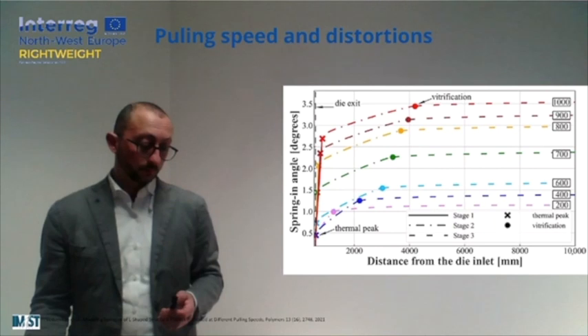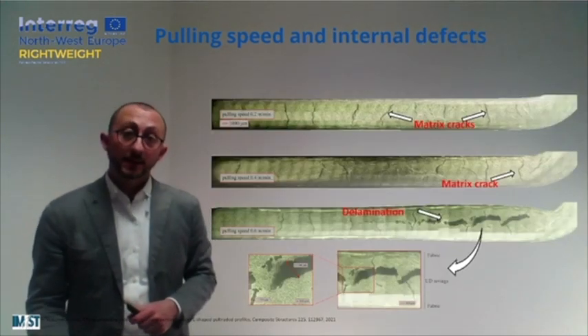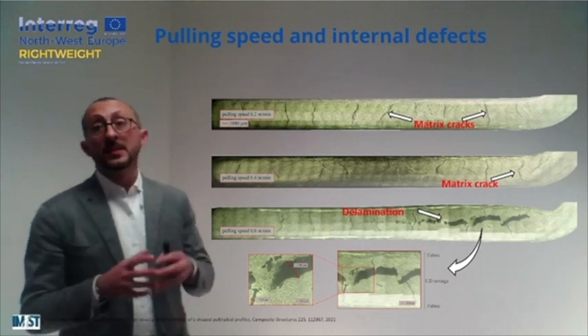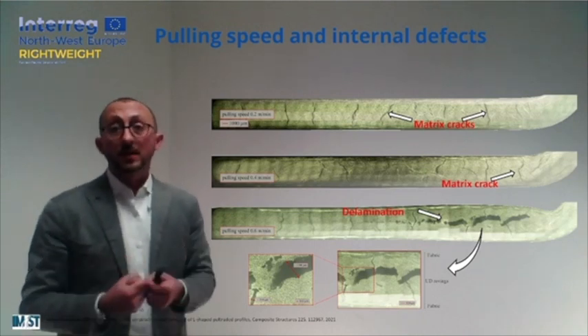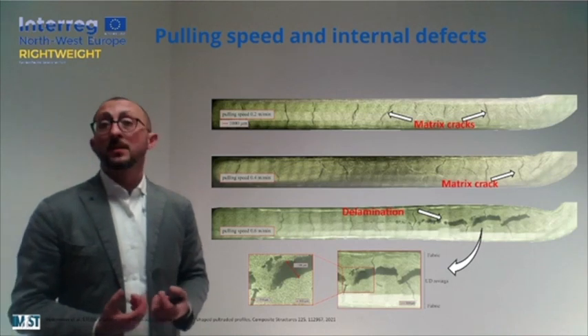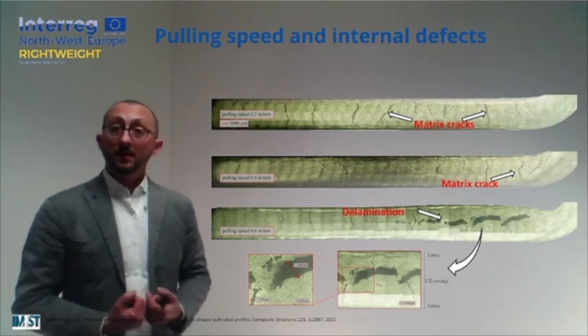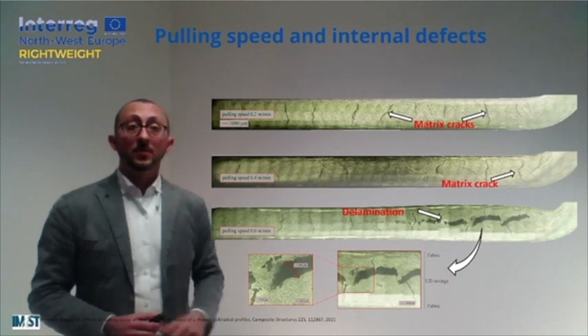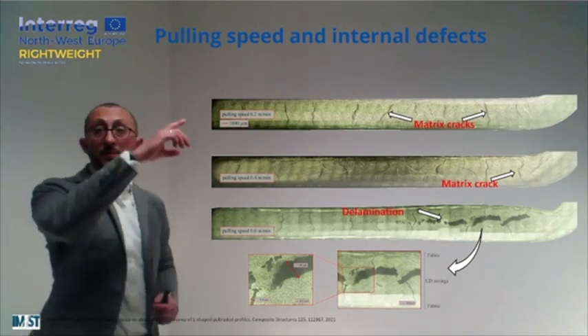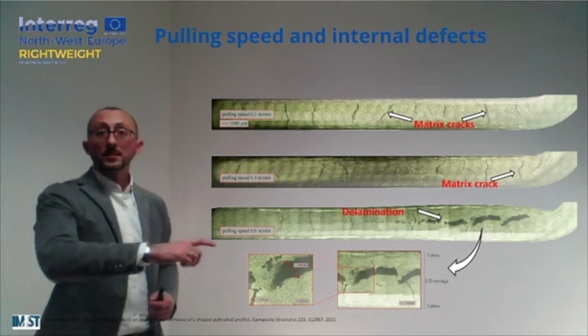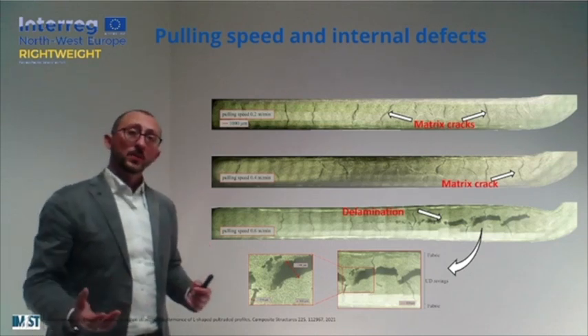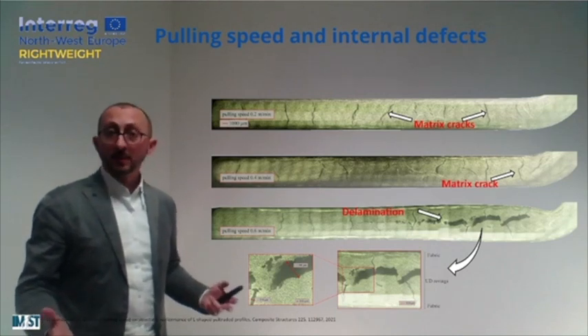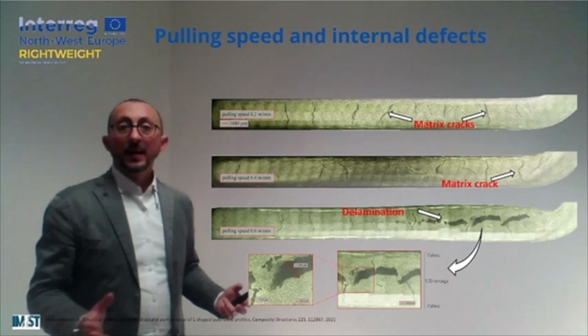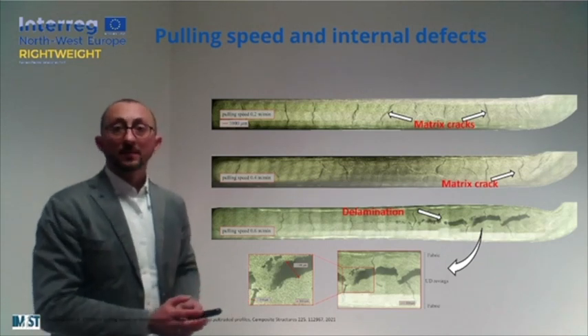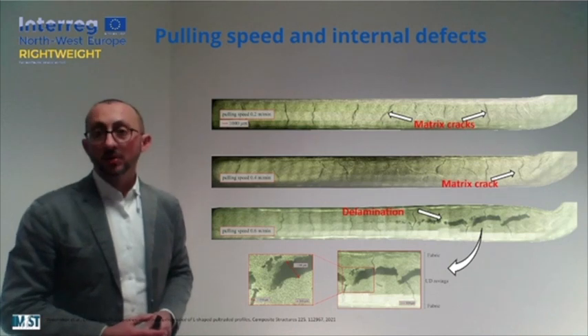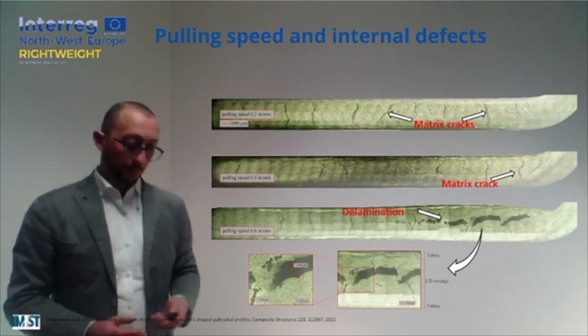Also, apart from distortions, there is a huge impact of the pulling speed on the internal defects, because the local concentration of stresses will be the main reason for internal defects like matrix cracks or delaminations and so on. So moving from this image here to the others, what we are doing is just increasing the pulling speed using the same heating profile, and the amount of defects that is characterizing each cross section is quite heavy.